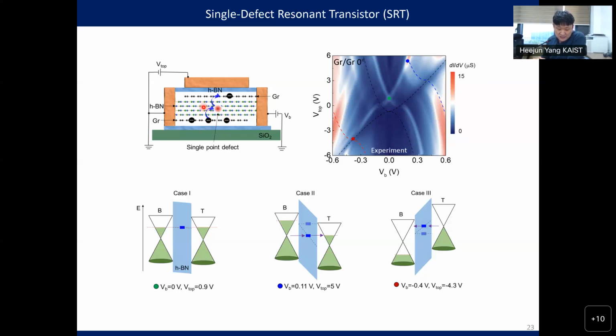Here, you see we are using graphene edge contact to reduce the contact resistance. And then we have tunneling. And you see some hopping-like things. This is tunneling. And we are doing some top gating of the top graphene layer like this. Okay, this is the experimental result.